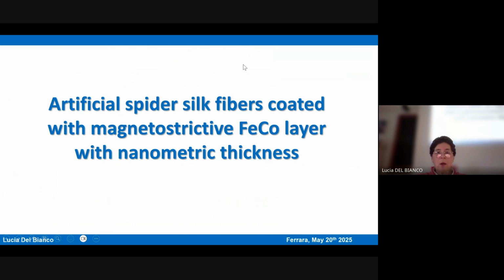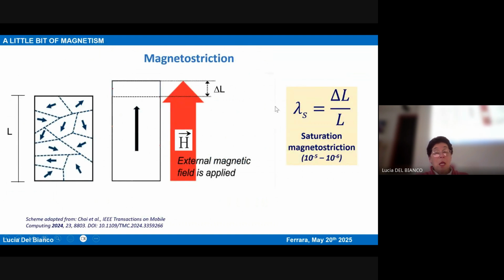So the second class of system, I should go a little bit fast on the second part, are silk fiber coated with a magnetostrictive iron cobalt layer with a nanometric thickness. So here I would like to explain what a magnetostrictive material is. If you have a ferromagnet, so again, a little bit of magnetism. If you have a ferromagnetic sample, not all ferromagnetic samples show this behavior, but some ferromagnetic materials show this particular phenomenon.